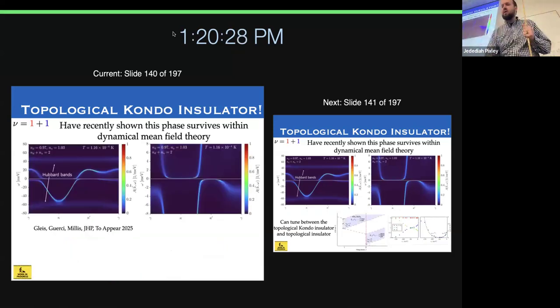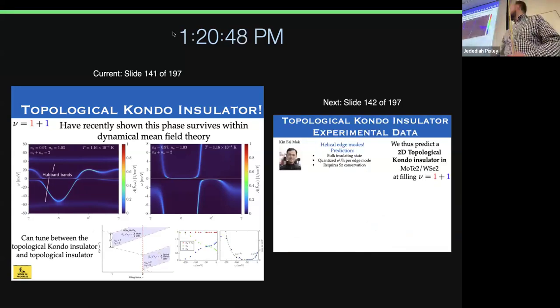But before I do that, let me just mention, I mentioned this already, that we can do dynamical mean field theory. And so we can go beyond this parton construction, get this dynamical linearization. So this is showing that this topological Kondo insulator is stable beyond the mean field limit. And here's the spectral weight of these bands that you now have within dynamical mean field theory. And so this is really worthwhile because the experiment is now tuning between these regimes. So in this experiment they're tuning from a topological Kondo insulator to a topological insulator to a trivial insulator. And you can't capture this within partons.